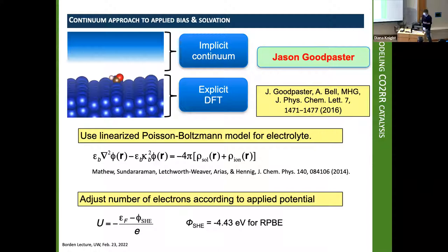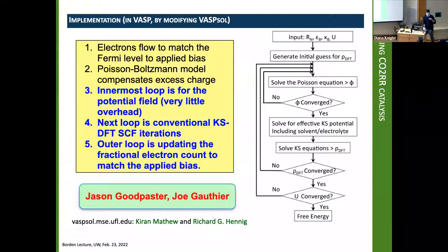And that will then add an extra loop to the normal self-consistent field iterations of Kohn-Sham theory. And there's yet one more inner loop that is making the continuum solvation self-consistent. So this is really a triple loop in the end compared to the normal single loop. And then if you do a geometry optimization, it's a quadruple loop. But it can be done, and that's what we do. We use the VASPsol package, and the electronic structure is done within the VASP code, which is a very good plane wave code.